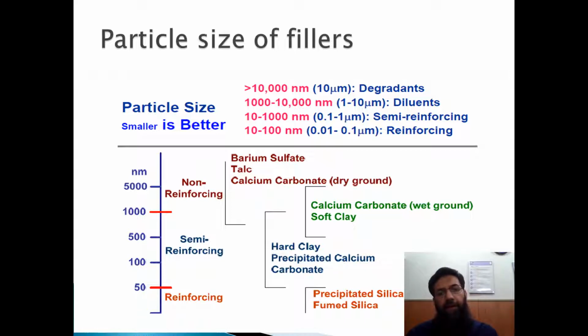Whereas the precipitated calcium carbonate and the kaolin clays are the semi-reinforcing fillers which are used in our local automotive part manufacturing industry. There are few fillers, such as dry ground calcium carbonate or talc. They have a particle size greater than a few microns, and they are mostly classified as the non-reinforcing filler. If we talk about the nanofillers, the precipitated silica and the fumed silica are the main reinforcing fillers in our industry. Carbon black is also widely used, mainly for the black parts.